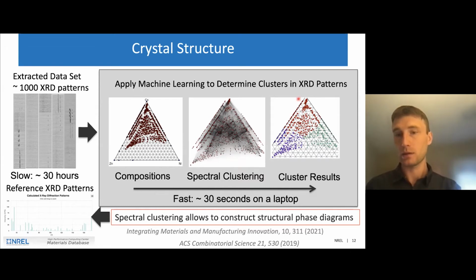So this ternary plot here represents, for the same composition space, a prediction of what the phases would be in this space. There's one specific red phase here that we know is a spinel single phase, and then two other phases: spinel plus rock salt, or spinel plus wurtzite. So essentially, applying this machine learning algorithm, this spectral clustering against our composition and structural data, lets us create structural phase diagrams, which is very useful because that's the type of information that can be directly compared to, for example, convex hull calculations or more advanced temperature-including convex hull calculations from theoretical databases such as the NREL Materials Database or any number of other ones.